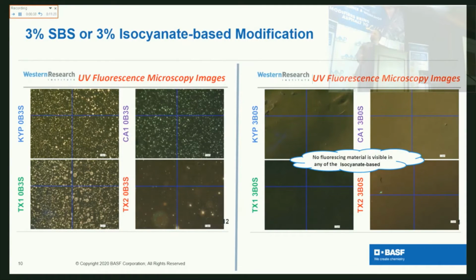And then we took that and said, okay, well, what kind of reaction was that? Because we didn't know at the time. We sent it up to WRI and requested some research to be done and said, so these are the 3% SBS modified materials. Let's run some UV fluorescent microscopy and see what they look like. And then we took a 3% isocyanate-based modification and requested the same.